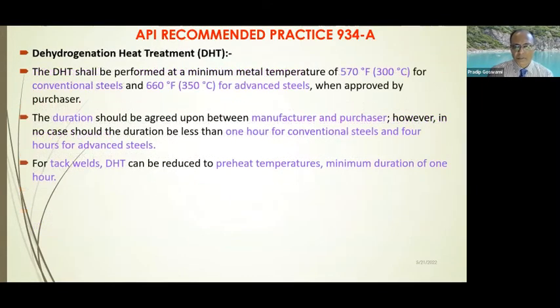Now, sometimes people may think, okay, instead of the ISR, why not do the DHT, dehydrogenation heat treatment? And DHT involves continuous heating to a temperature of 300 degrees centigrade or 350 degrees centigrade, for 1 hour minimum, or 1 to 4 hours minimum. But whether it is DHT or ISR, it is again the end user's or the purchaser's call, and the fabricators definitely have to fulfill the requirement. But from my experience, between DHT and ISR, intermediate stress relief is the preferred and conventional method for these reactors.